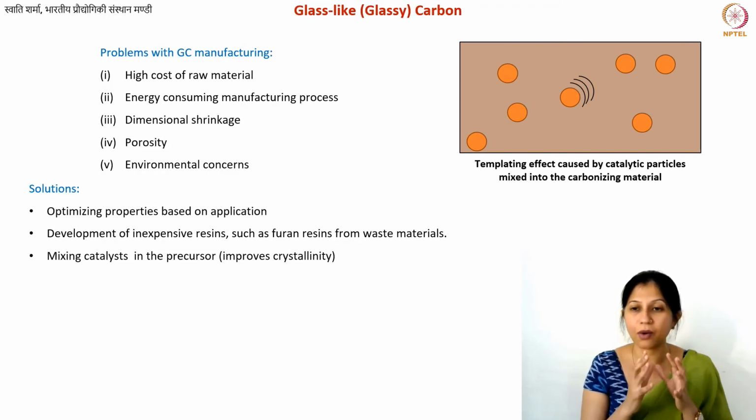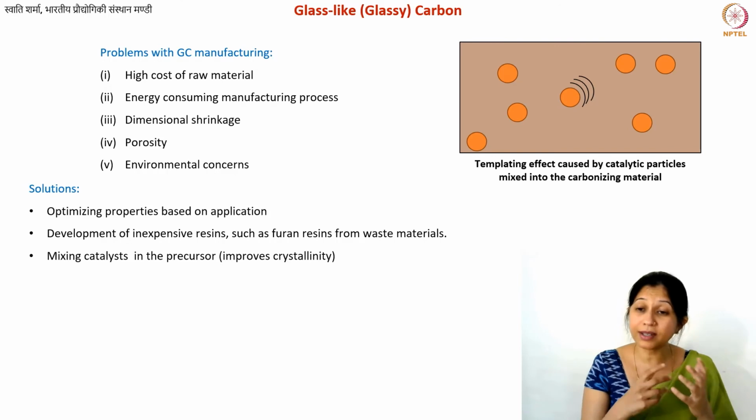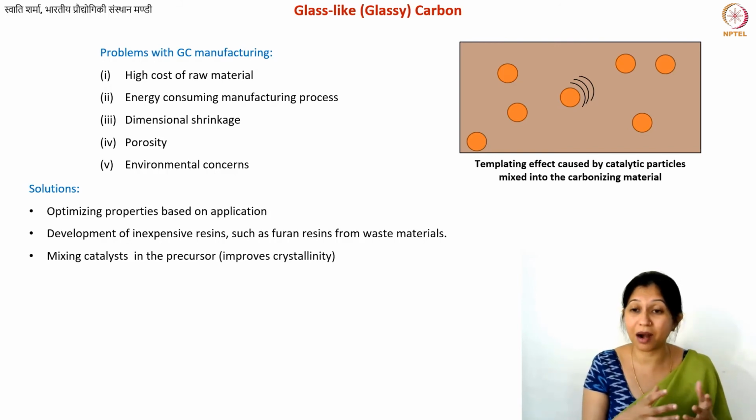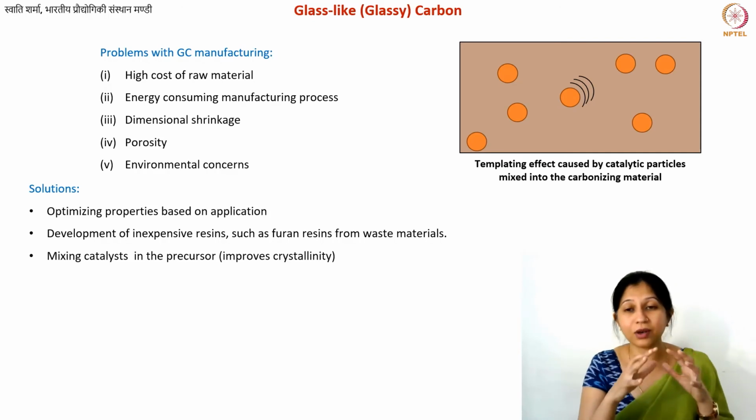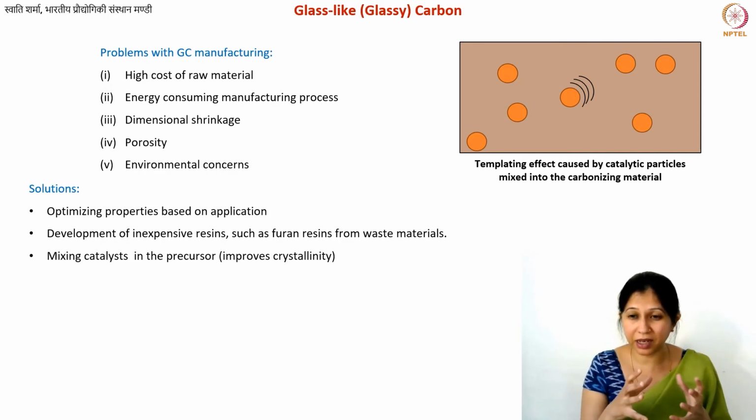This is one proposed mechanism. However, you do see that around your metal particles, or sometimes people even use other carbon nanomaterials as catalyst, around those things you see more graphitic regions, which means you see a higher crystallinity, so higher short range order. Altogether you have a disordered carbon material, but you still have certain short range order.